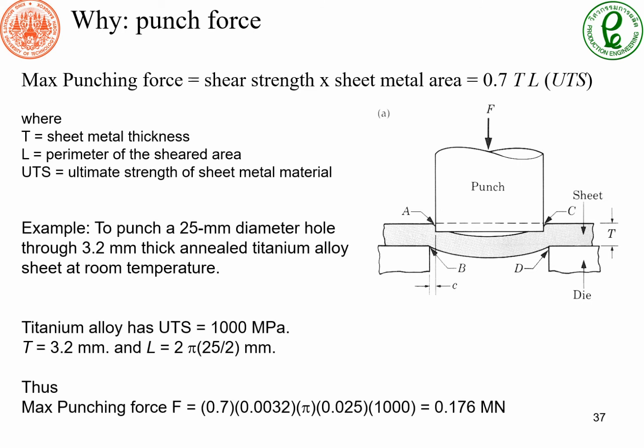For example, to punch a 25 mm diameter hole through 3.2 mm thick annealed titanium alloy sheet at room temperature, titanium alloy has ultimate tensile strength of 1000 MPa. So we can calculate maximum punching force to be about 0.176 meganewtons.